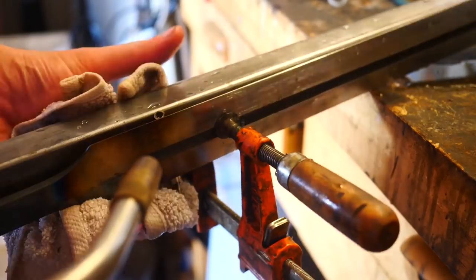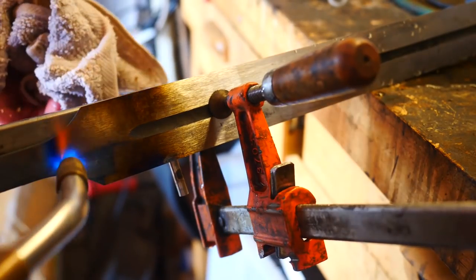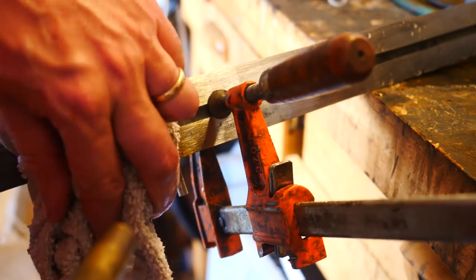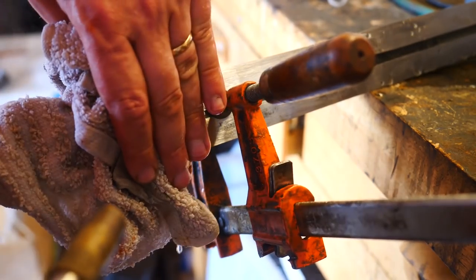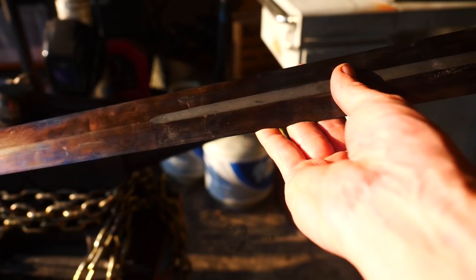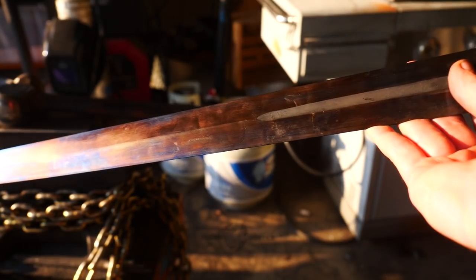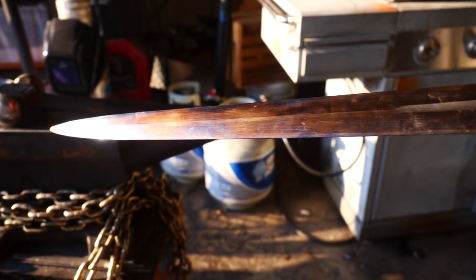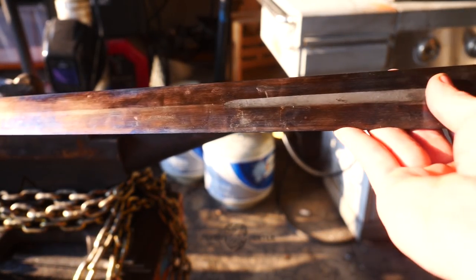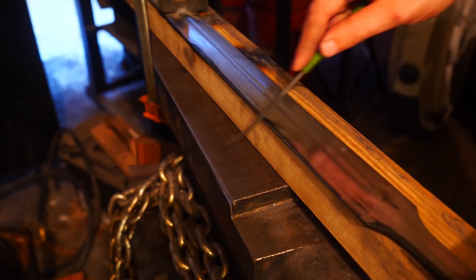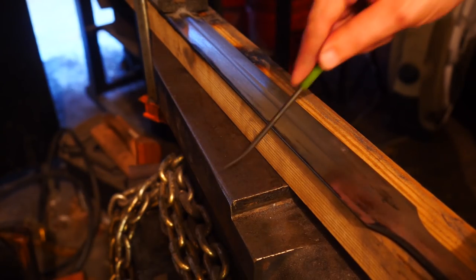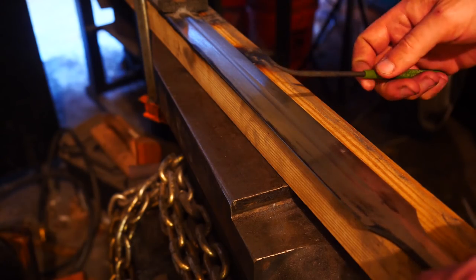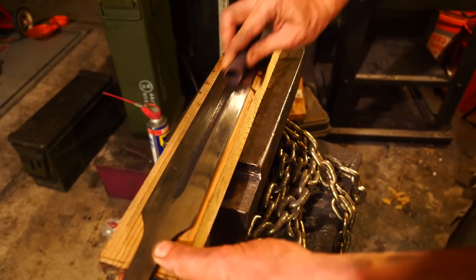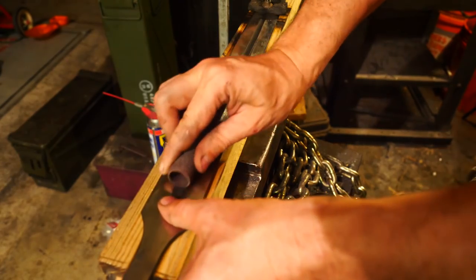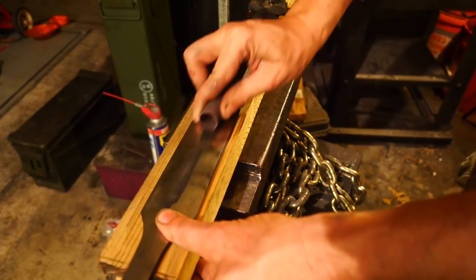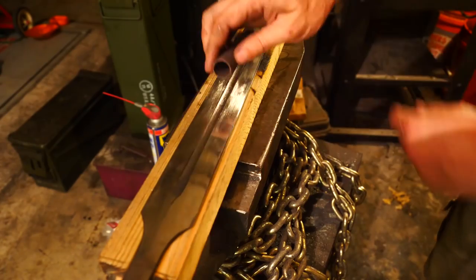These tempering cycles are barely adequate. You know, they're not long. They're not an hour long, which probably is a minimum for this type of steel. They're not very consistent, although here you can see I got a little more even distribution of the colors than in the past. And, you know, it's pretty marginal. A marginal heat treat, but acceptable. It still skates this 50 HRC file all up and down. So I have no doubt that it's not a completely uniform heat temper cycle, and it's not a good temper cycle, but I suspect it's adequate.